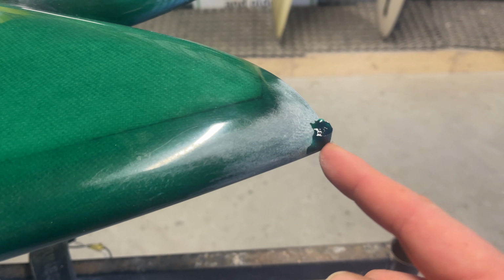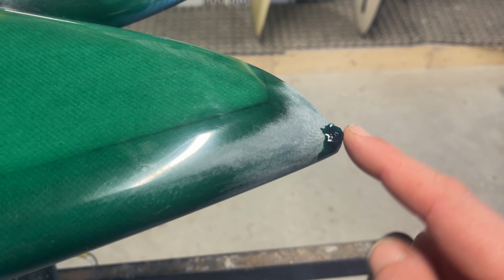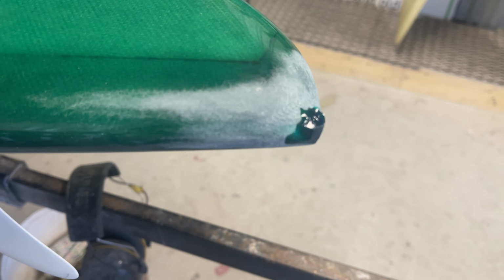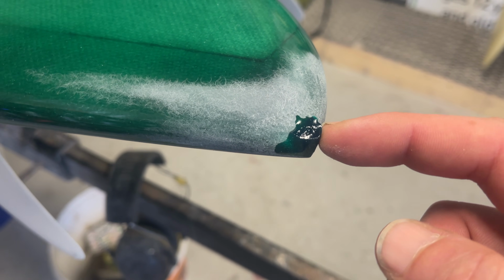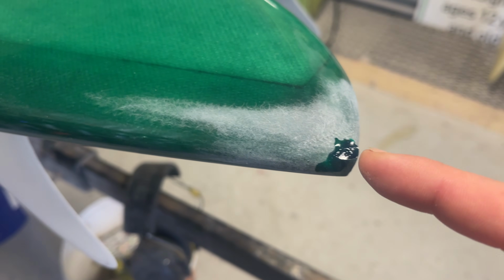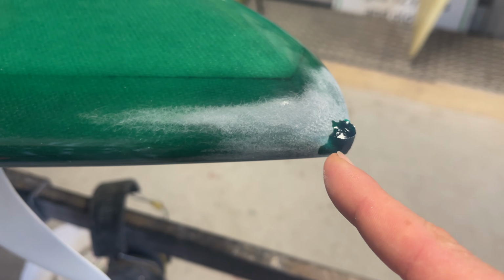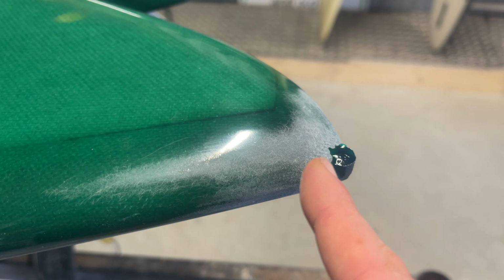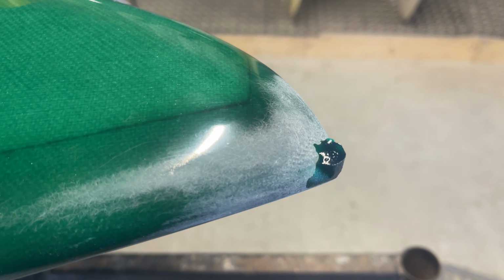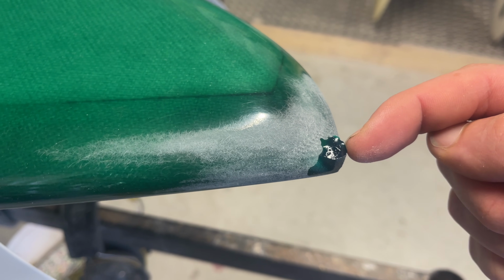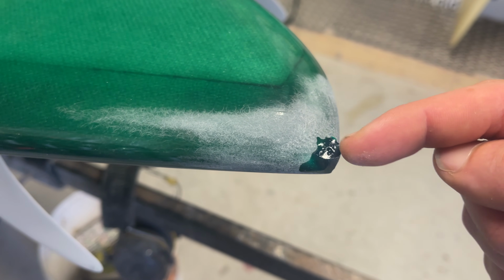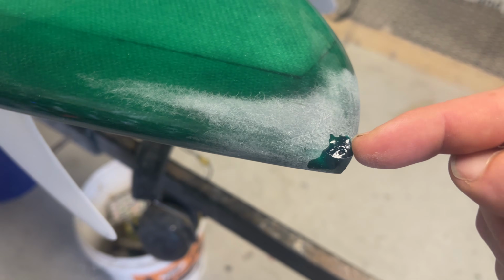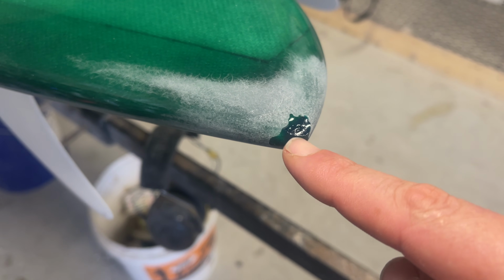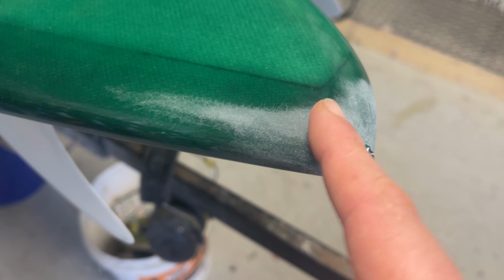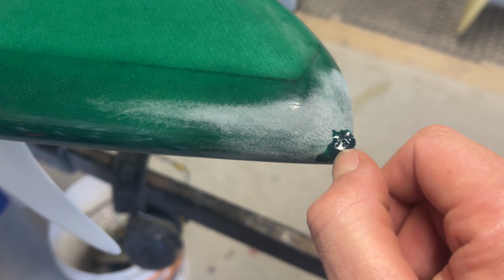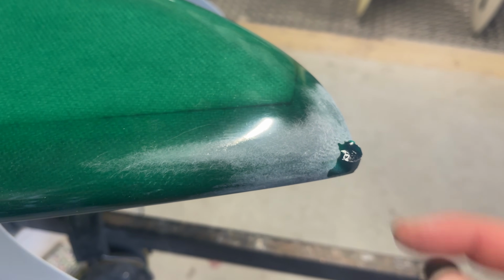So of course we have over-filled this ding quite a bit, so we need to sand it back down to shape. It is worth noting though that, let's say for instance we had under-filled this ding and there was still a bit of a hole here. We cannot pour more sanding resin or any type of resin on top of this sanding resin we've just poured. It won't adhere. Before adding any kind of material to this resin, be it cloth, poly resin, epoxy resin, sanding resin, laminating resin, we need to sand this to make it all scratched and keyed up like it is here. Otherwise there just won't be good adhesion with the next material we put on top.